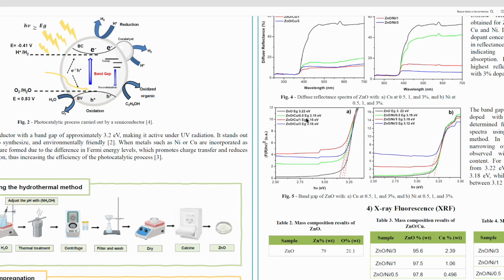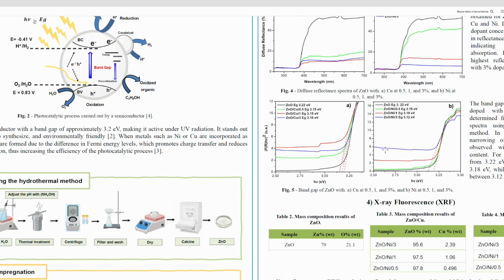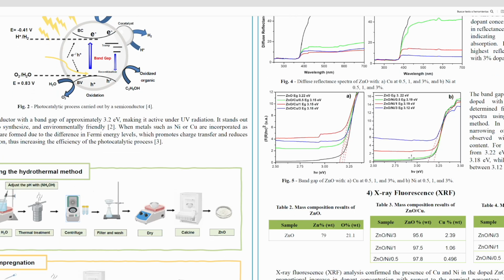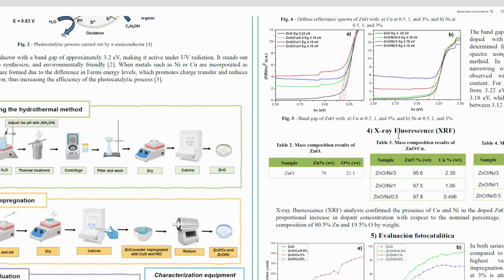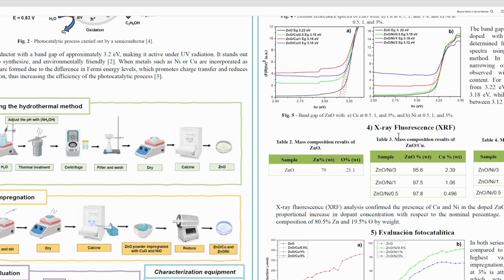In figure number 5, once we performed the diffuse reflectance characterizations, the band gaps were calculated, which are practically very, very imperceptible. For example, for pure zinc oxide, we obtained a band gap of 3.22. For zinc oxide with 0.5% copper, we obtained 3.15, and successively with 1% and with 3% copper, 3.18. So there were no apparent modifications, just very small ones, honestly insignificant. For nickel, we also obtained 3.19, 3.19, and 3.12, which shows that there are no modifications in its band gap. It continues to respond to visible and UV energy.